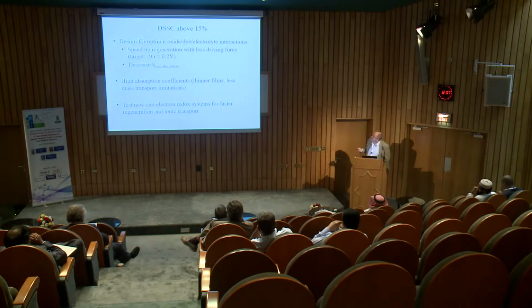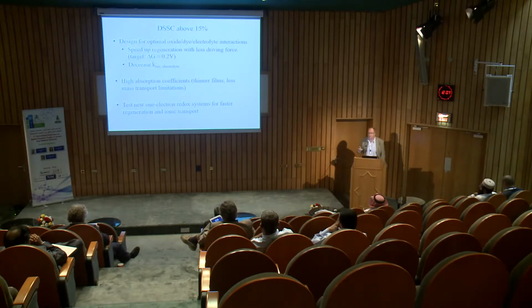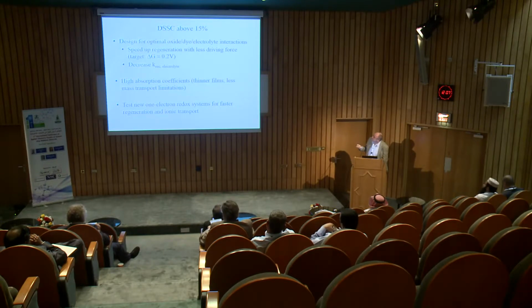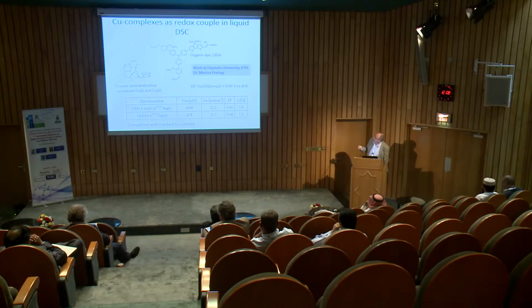To summarize, I would say what we are looking for to make higher efficiency than perhaps 15%. I would say ideally if we can go down to a driving force of 0.2 volt, that would be very nice, let's say. Then we can gain even higher voltage. And of course we need some other things. We still need to worry about recombination processes and so on. I will tell you that we think now that we have one possibility with a copper complex instead of cobalt to regenerate efficiently. This work is actually not published yet, the liquid results.